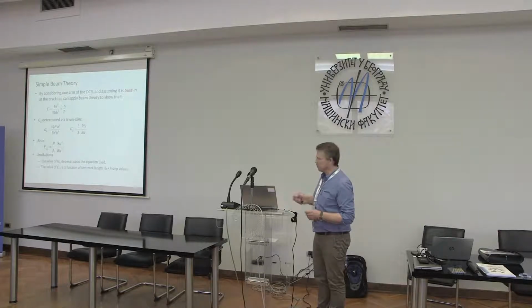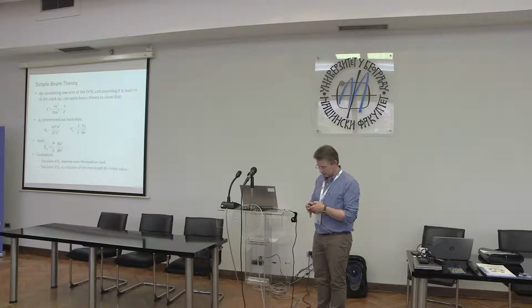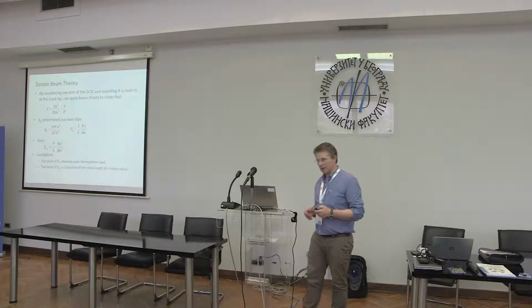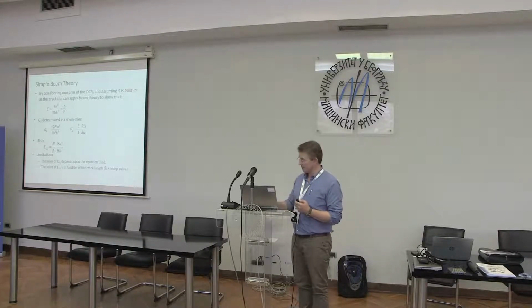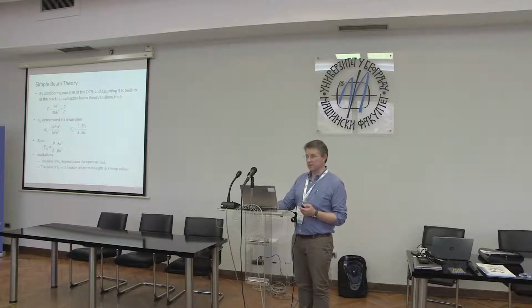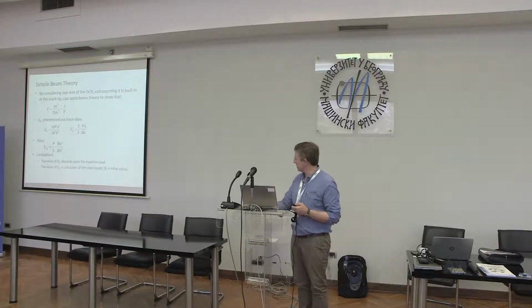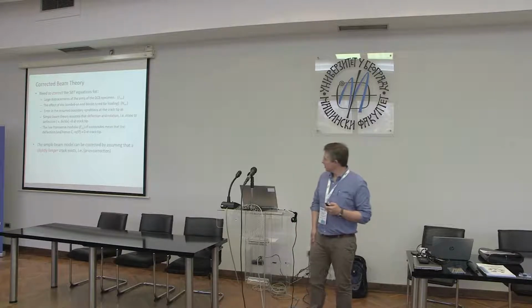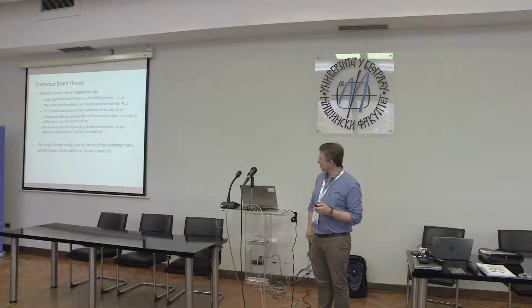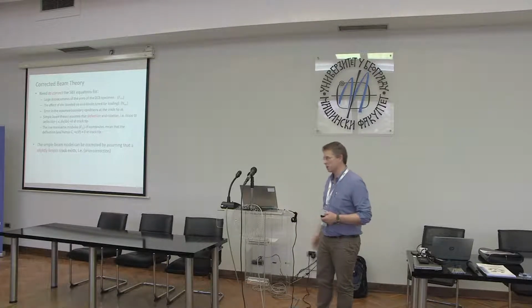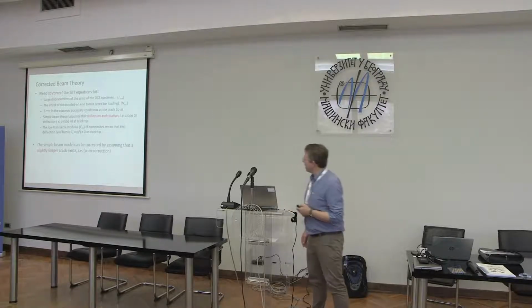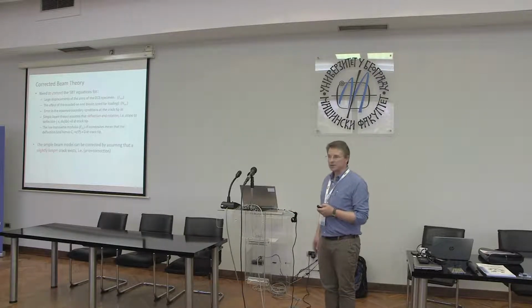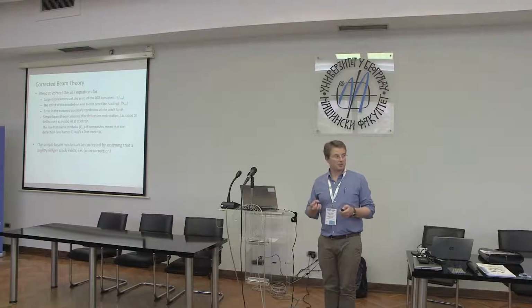What you do if you use that simple approach, of course, is that you find a number of anomalies in the data. So something fairly early on was telling us that the assumptions we'd made were not correct in this case. So the corrected beam theory, which was built into that work that Gordon Williams talked about, was really to recognize what was wrong with the simple beam theory.